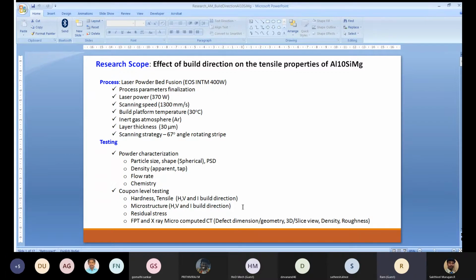And apparent density is a measure for understanding the powder packing and the flow rate. Similarly, tap density. If you have a higher apparent density, your packing will be better and flow rate will be better. And for flow rate, we use a Hall flow meter to measure it.